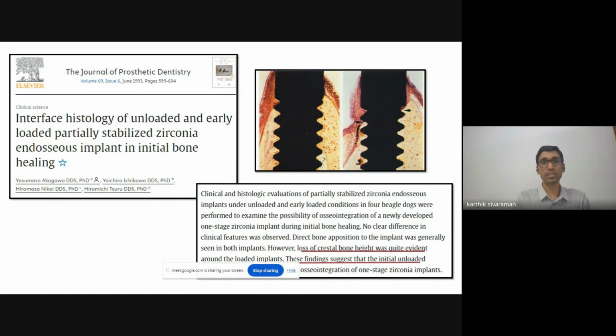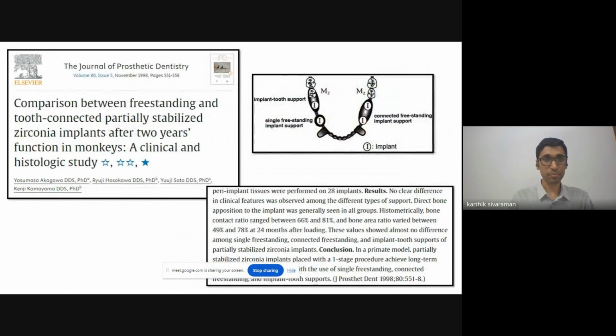What they found here is that there was appropriate bone implant contact in both cases. However, there was bone loss in the implants which were loaded early. And that's why the recommendation came that one-piece zirconia implants should not be loaded early. Otherwise, it can impair the osseointegration rate. So this study could basically establish that there is a reasonably good level of bone implant contact. The next step was to find whether this could be sustained over a greater period of time.